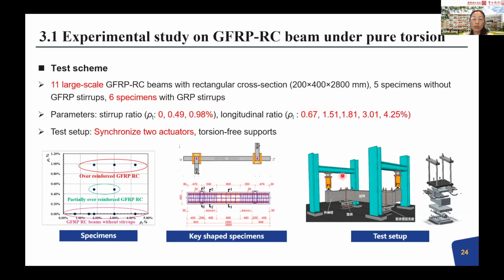And here I want to mention that for this test, especially the following test with combined torsional loading, we have developed the test system, and we have collaborated with a testing company to make sure that the multiple actuators can synchronize during the testing. And also we developed the torsion-free support under the beam, which allows free extension in the longitudinal direction, and also free torsion when the beam is under twist. So for pure torsion, here you will see that there are P1 and P2, 2 actuators, and they were synchronized, meaning that the forces between these 2 share the same ratio, FP1 equal to FP2.